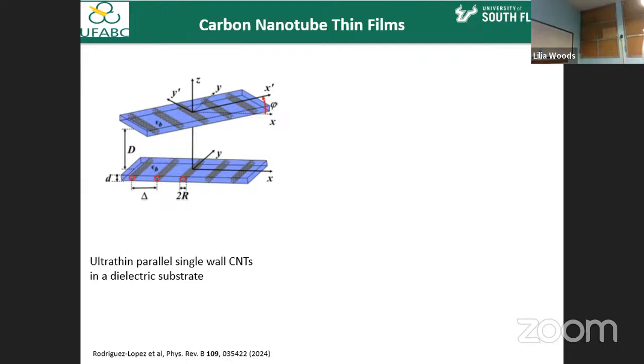So my thought process was, if I look at now not one carbon nanotube, but make a metasurface like here, I have many parallel single nanotubes placed on the substrate. Maybe it's not exactly two-dimensional, but this ultra thin film can be even better to observe experimentally. So I'm going to look at these ultra thin parallel carbon nanotubes on a substrate, and the first thing I want to do is determine the dielectric response.